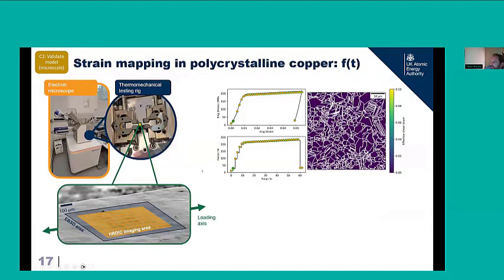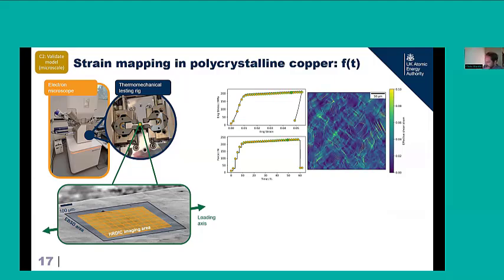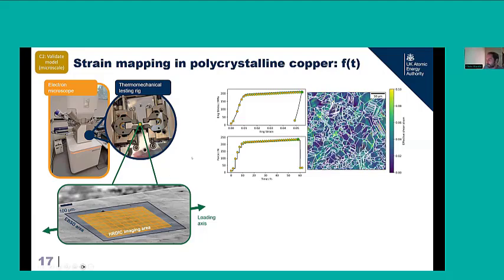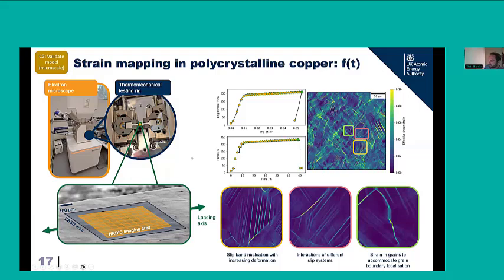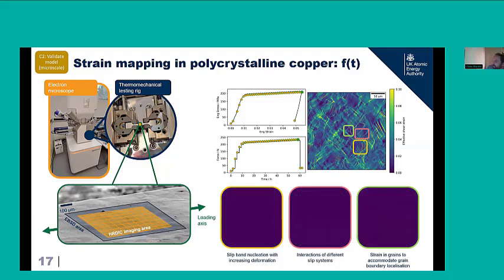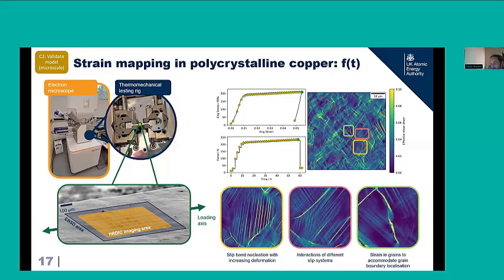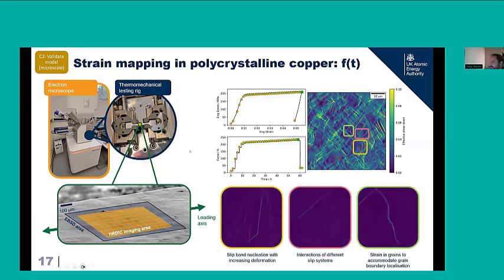And we can do this not just as a single snapshot after deformation, but as a far better function of time, or more directly as a function of strain. So this just shows a polycrystalline copper sample being deformed as a function of high resolution strain, and seeing how those different deformation mechanisms evolve through that experiment. And of course, we can do a similar thing where we zoom into different regions of interest and see how the different deformation mechanisms evolve with strain and how they interact with each other. Again, really important for validating our models.